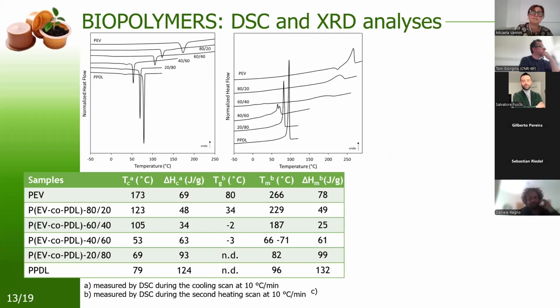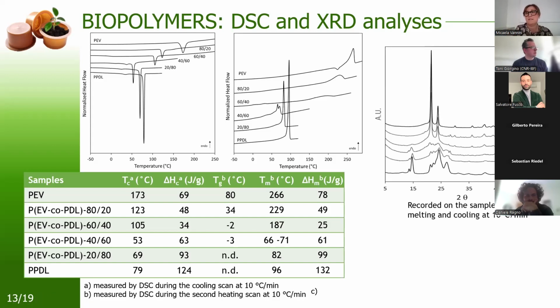From DSC, it's clear that only one amorphous phase is present in the copolymers, because only one Tg is recorded. And from X-ray diffraction, we deduced that only the crystallization of the prevailing component takes place, and the crystallinity extent decreases in the copolymers. The direct result of this behavior is that the copolymers are less crystalline, so less brittle, and therefore they are processable.